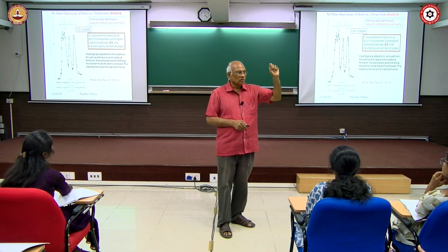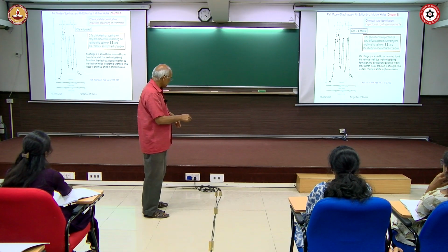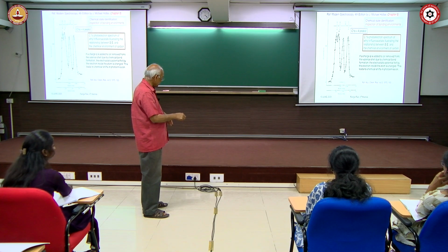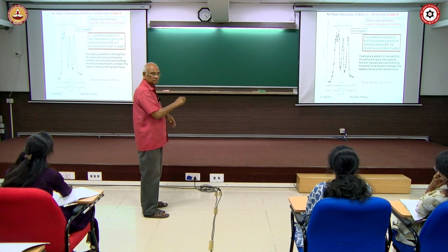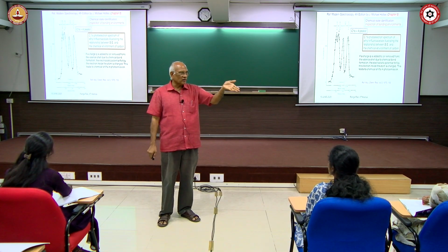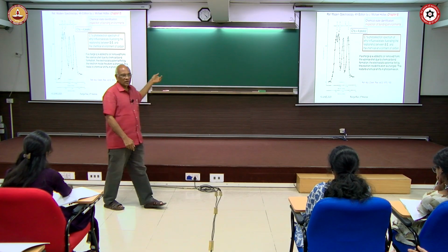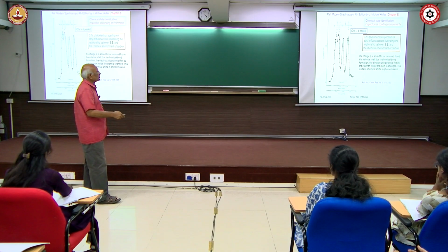Carbon attached to fluorine. You can see here, this is the highest binding energy, around 294 or something, and this one is only 284. So this is chemical shift. The same thing you have heard in NMR. So this is chemical shift in photoemission spectroscopy.